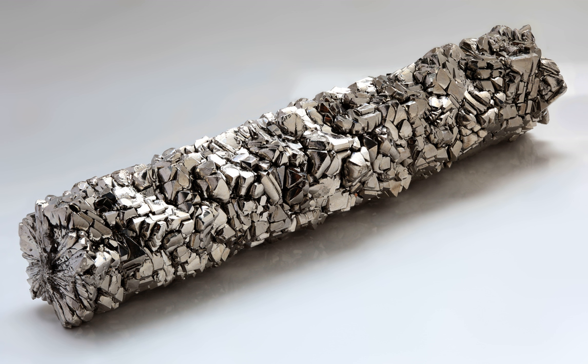A more recently developed batch production method, the FFC Cambridge process, consumes titanium dioxide powder, a refined form of rutile, as feedstock and produces titanium metal, either powder or sponge. The process involves fewer steps than the Kroll process and takes less time. If mixed oxide powders are used, the product is an alloy.